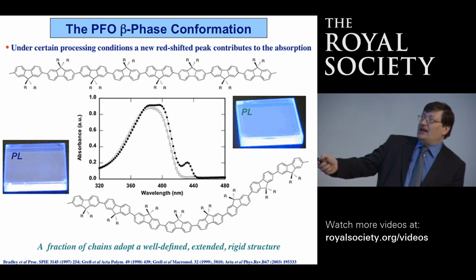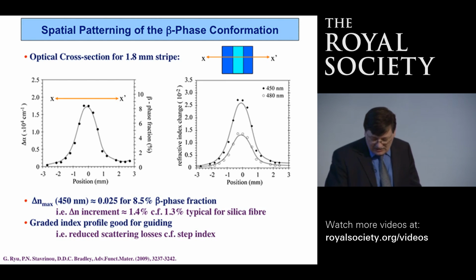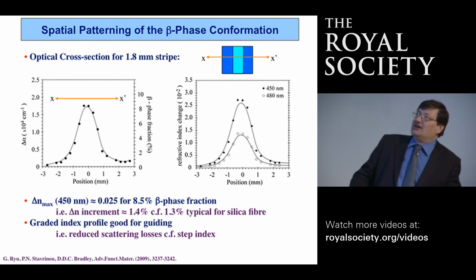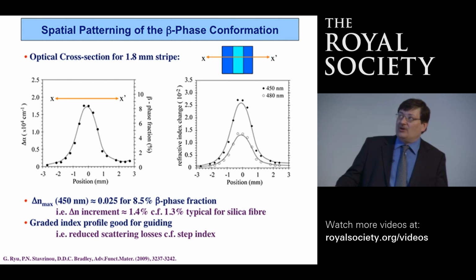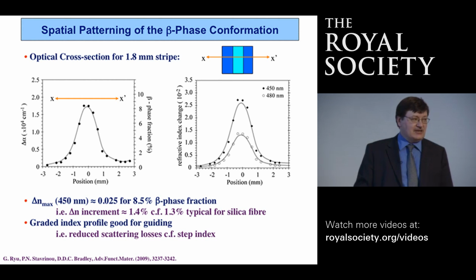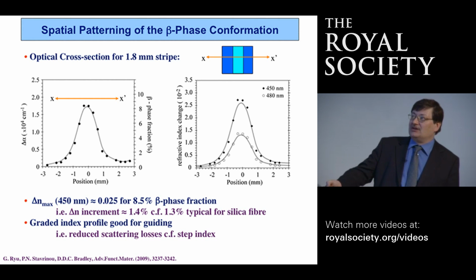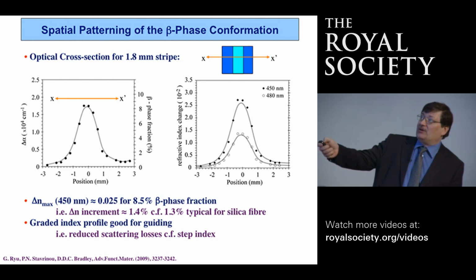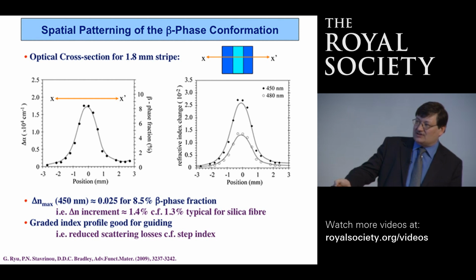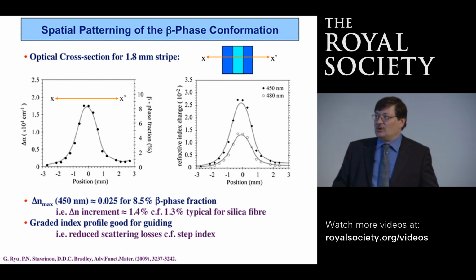And if we look at the luminescent output, we can quite clearly see the contrast. So this is a sort of turquoisey color. In this case, we have a typical blue color. So the question is, can we spatially structure that? And the answer is yes. And this is just one example of doing spatial structuring, where we've used a masked exposure to a solvent to generate this conformation. And so this is a cross-section through a stripe where we've generated the beta phase conformation in a sample. This is looking at two different wavelengths, so we can see that the refractive index variation changes with wavelength. Basically, we end up, in this case, with a refractive index contrast of about 1.4%, which is quite similar to the sorts of refractive index contrasts that are found in typical silica fibers.